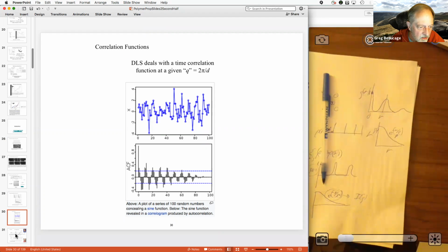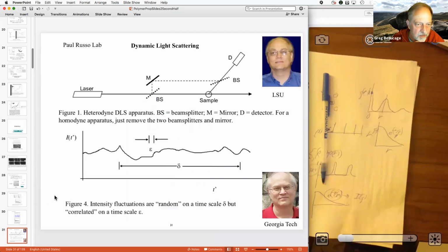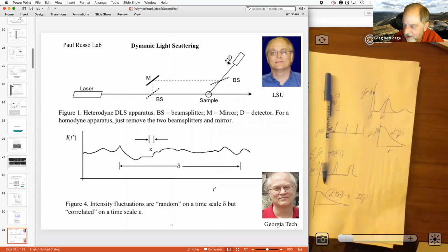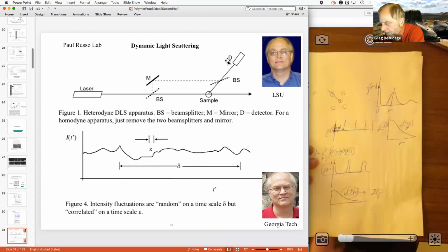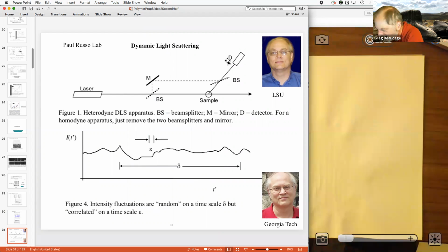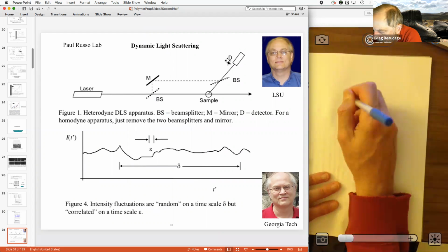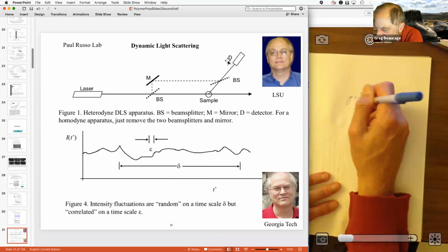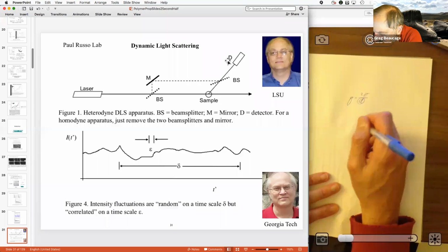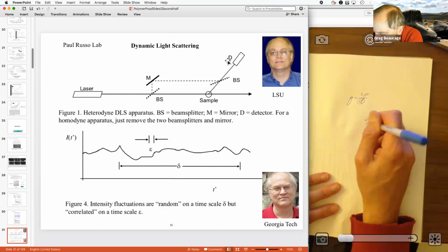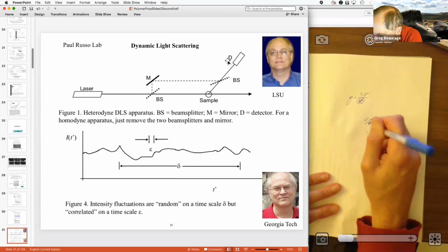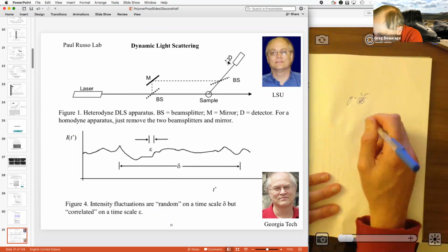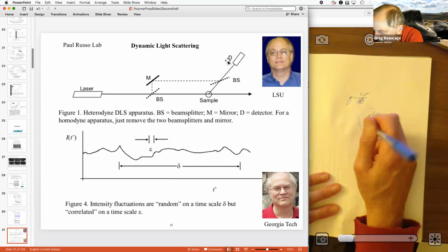Anyway, in dynamic light scattering, you use a correlation function, the same kind of thing. You shoot a laser beam at a sample and pick up at some angle, right? And that angle is related to some size scale. At that angle, we have Q is 2 pi over some size d. So we're taking the material which has things in it, and we're throwing in a rod of size d, or size r, say, change d to r. We're randomly putting that into the system because these things are moving around with kT all the time. So we're measuring the size r time correlation of these particles.